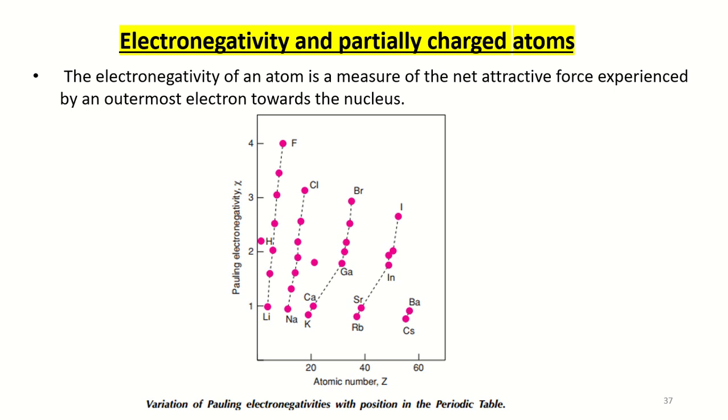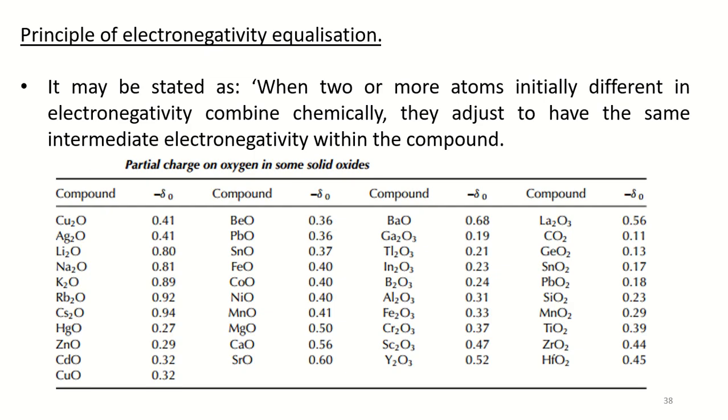The length and strength of this interaction, and hence the degree of covalent bonding which results, is again related to the electronegativity of the two atoms. Thus, electronegative cations such as aluminium 3+ are much stronger electron pair acceptors, which would be treated as Lewis acids, than electropositive cations such as potassium.